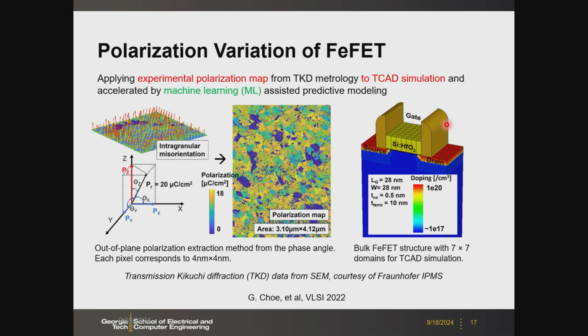Another challenge we mentioned earlier is the variation. Especially when you deposit the ferroelectric thin film, as deposited, there could be different polarization. First, different phases. Second, even for the same orthorhombic phase, you may have different orientations.